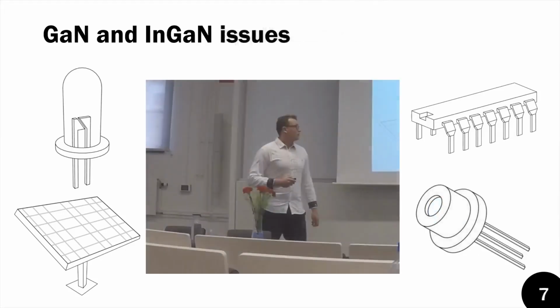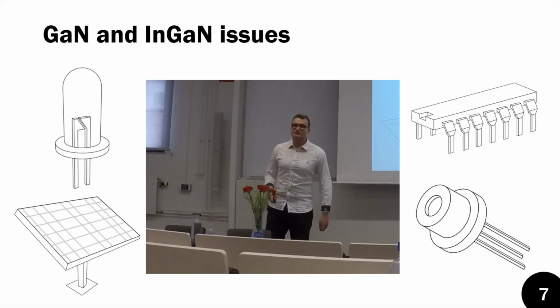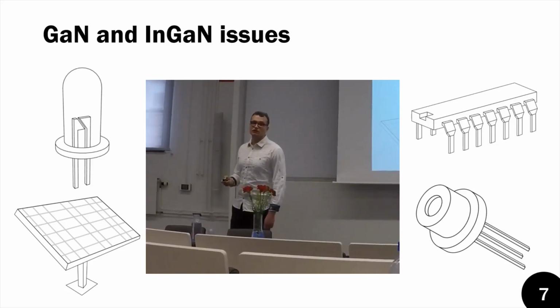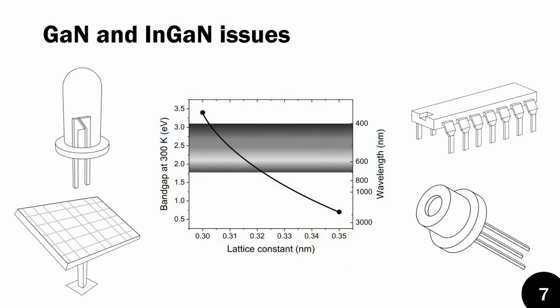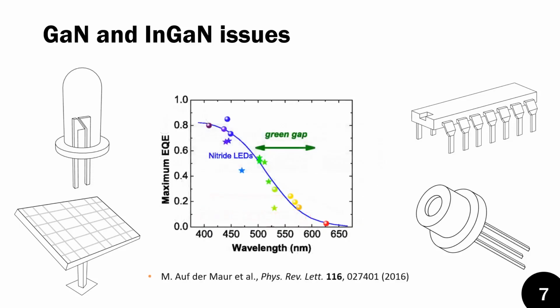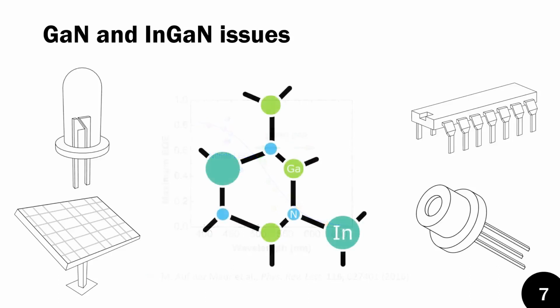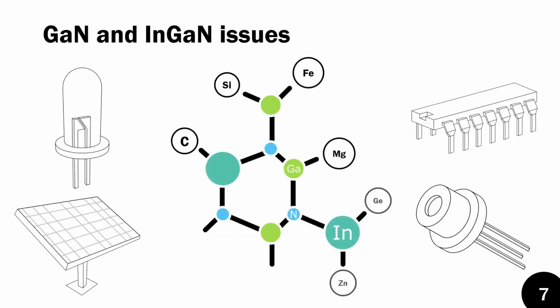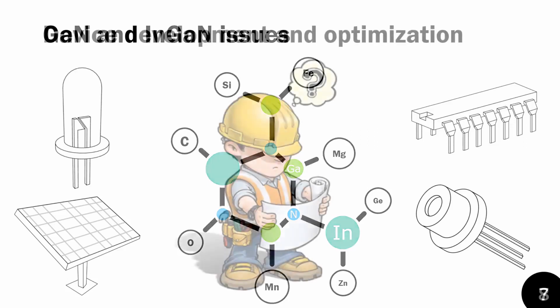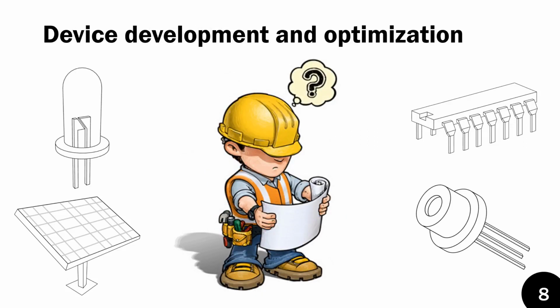Now, despite the success of all these devices, not all material properties are agreed on. There are still many growth-related issues that need to be solved. Most notably, InGaN growth experiences phase separation, which results in different indium incorporation rates at different sites of the sample. This, for increased indium content layers, results in the generation of a high density of defects, which is detrimental for light emitters in the green gap. In addition, the mechanisms of doping, how impurities are incorporated, and what energy states are introduced in the bandgap are not yet fully understood. These issues emerge during the device development and optimization phase.